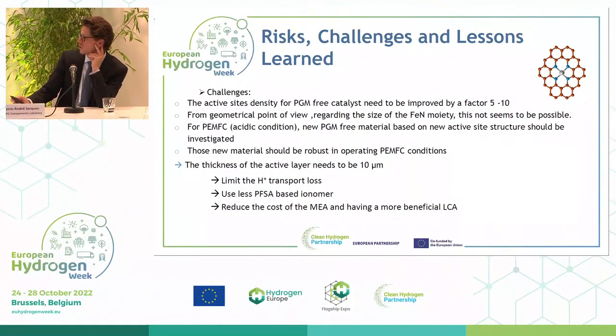Then, what are the risks, the challenges, and the lessons learned in that project? The challenges first, of course. The active site density for PGM-free catalyst is not enough, and that needs to be improved by at least a factor of 5 or 10 in order to be good. My personal point of view is that from a geometrical point of view, for PGM-free catalyst based on iron, nitrogen, carbon material, we've got this structure of the active site, and you cannot reach the active sites that will be needed to have a material as active as platinum on carbon.